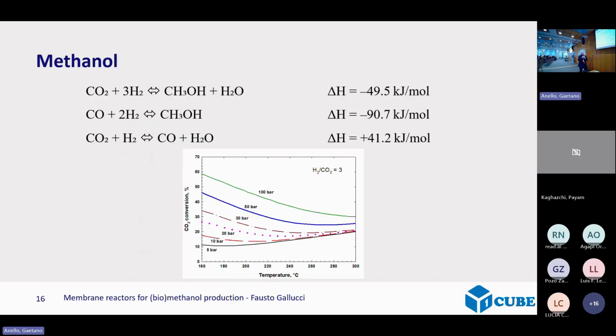Now, as I said before, because methanol production has hydrogen inside, these are the reactions and they are typical equilibrium reactions. So they are exothermic in total. And you see that you need very high pressure because you proceed with a decrease of volume to get a good equilibrium conversion.